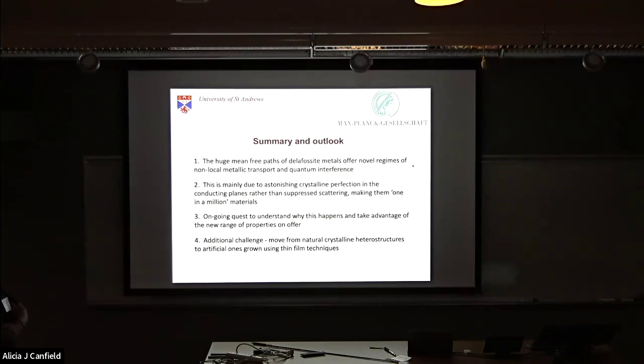Yeah, we've been doing a lot of work on that. Graham Baker has really helped my understanding of these issues. I think I'm responsible for introducing "momentum conserving" to the literature, and that's a terrible term, so I apologize to the world. Because you don't need pure momentum conservation to get these apparently viscous effects. So if you imagine, it's been done, I think it was even done in Landau and Lifshitz, to decompose into Fermi surface harmonics, right? The second harmonic is the thing that, with scattering in the second harmonic channel, will give you a viscous-like response. And what we believe here, Graham's even modeled it, is it's because we have all of these out of plane impurities, and they're giving very, very shallow potentials in the plane. So it's an impurity scattering, it's not temperature dependent, right? But it's momentum conserving enough to put a big term into the second harmonic.